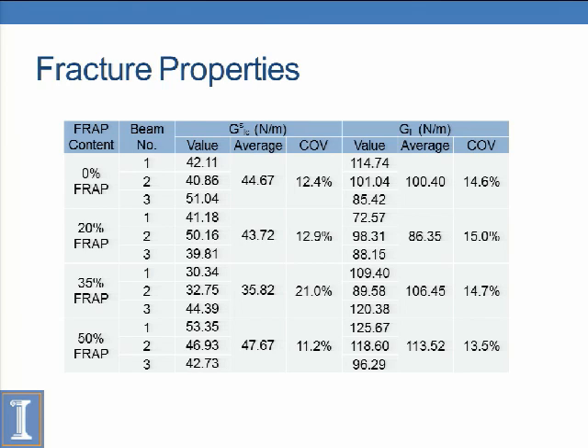And then if we look at our total fracture energy, the total work of fracture, it is somewhat unaffected. It may be a little bit higher at higher FRAP contents. That probably warrants further study to confirm. But relatively, we concluded the fracture properties were unchanged by adding FRAP, which is a very important concept considering we have a reduction in strength and yet our fracture properties are unaffected. So that might actually tell us that when we test a slab, we may have similar properties between the virgin aggregate and the FRAP aggregate concrete.